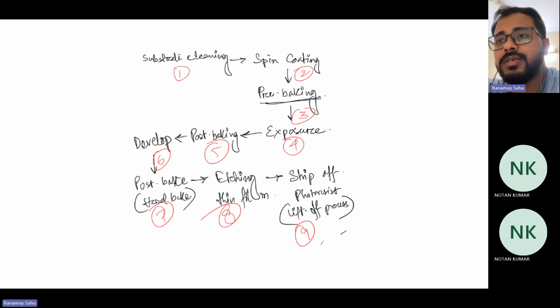and then you do the pre-baking to make sure that the cross-linking has happened nicely, and you do the exposure process where the light strikes the coated substrate surface. You do the post baking again to make sure that there are no loosely cross-linked structures in the desired region, and then you do the developing process where the undesired material is washed away. You again do the hard baking process, and you do the etching often if you want maybe to etch some material out of the substrate.